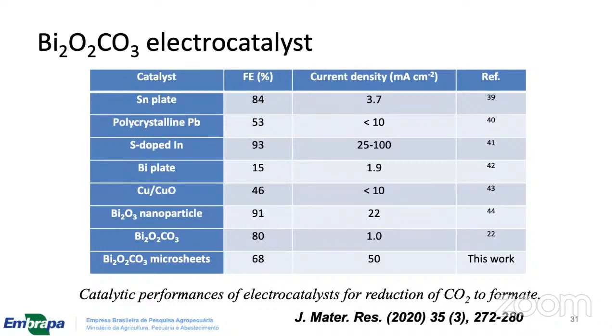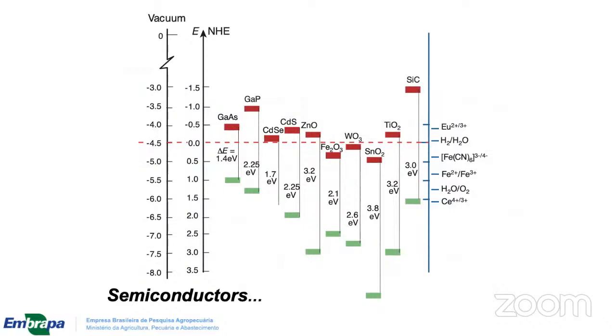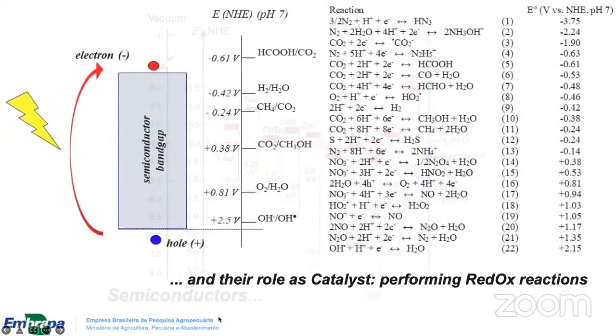But again, in terms of catalytic discovery, we need to use some kind of reference to understand how this catalyst could be interesting or not to produce CO2 reduction. And in our opinion, semiconductors are more interesting in this way if they are directly excited by an external source of light. The most important thing for us in the selection of semiconductors is to understand where the conduction band of the semiconductors is in terms of these reduction reactions. Think of the system like an electrochemical cell, but an electrochemical cell in a particle. Or in other words, if the semiconductor receives the light, the electron is available to produce a reduction reaction, and the hole is available to produce an oxidation reaction in the same particle.